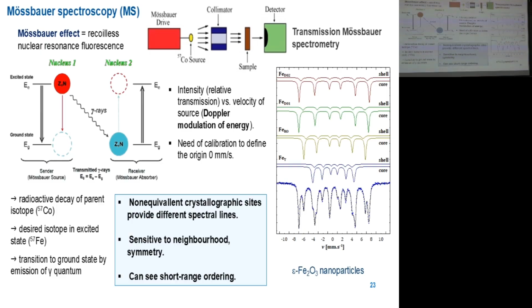So if you decide to prepare maghemite, fully oxidized iron 3+ oxide, then you needn't do Mössbauer spectroscopy if you are really sure that it is only iron 3+. However, if you are dealing with magnetite or with any system containing iron 2+, or especially when working with metal iron particles or with some iron nitride particles, you have to do this just to determine the actual oxidation state of iron.